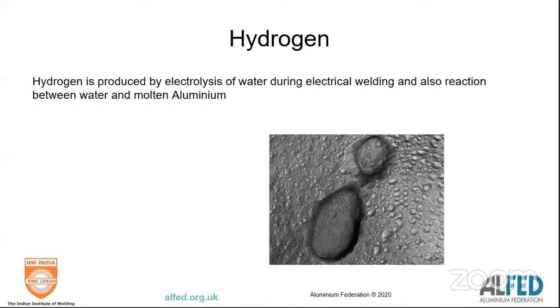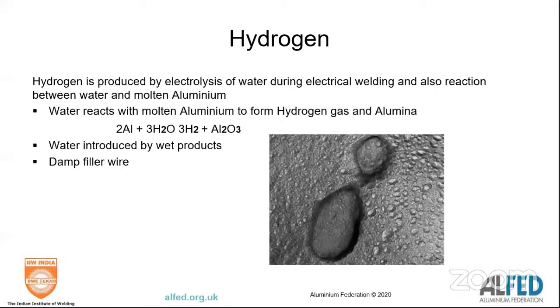Hydrogen is also produced during the welding process, particularly through electrical reactions, because when you've got damp atmospheres or high humidity and it's condensing on your weld area, when you pass the electric current through, what you'll have is electrolysis and produce hydrogen. Problems with damp filler wire.